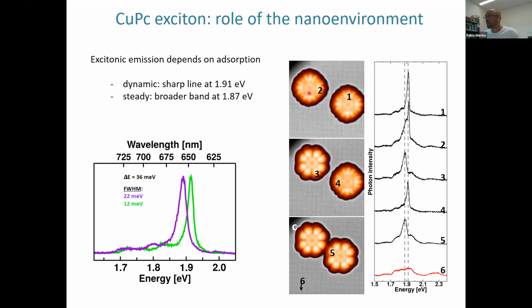And in this series of STM images and optical spectra, we see that when we take a spectrum on the dynamic state molecule on position number 1, we get this sharp emission. When we do the spectrum on the steady-state molecule on the left, what we get is the same line, but with a broader shoulder on the right hand side of the energies.